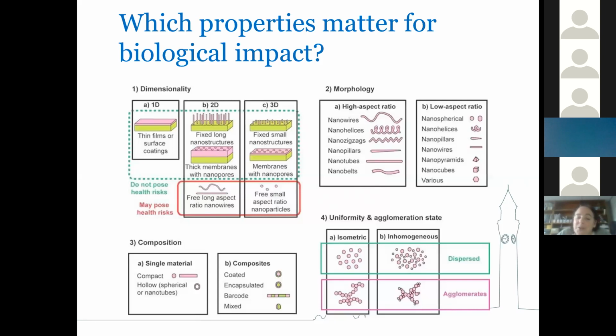Whether the toxicity comes during its useful or functional lifetime in the product, or whether it comes at the end of the product's life cycle, so when the phone is thrown away and starts to break down and the cadmium is then re-released to the environment. So if the element itself is toxic, it's quite probable that the nano form of it will also be toxic. And there are lots of strategies being developed for potentially reducing the toxicity of nanomaterials, which could be coating them so that there isn't any potential for release of the cadmium, for example, or mixed phase particles, and so on.